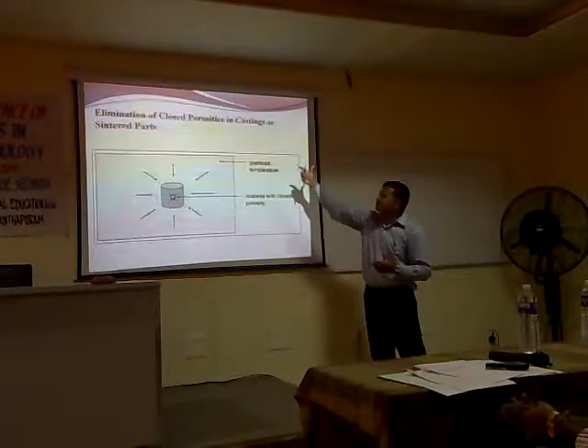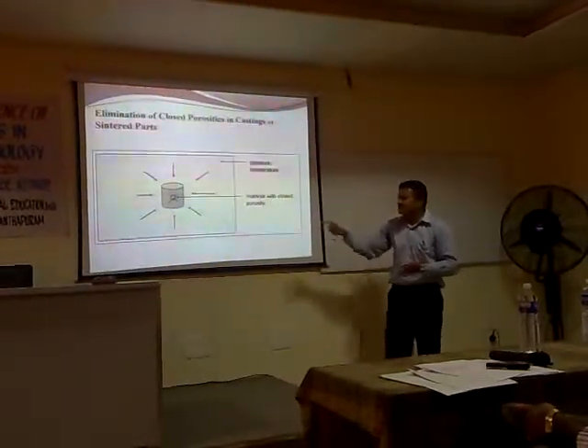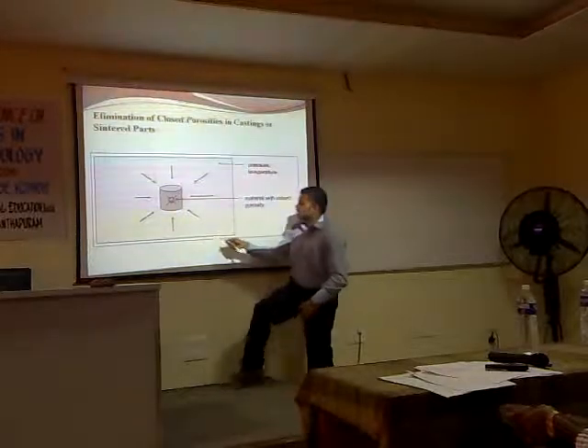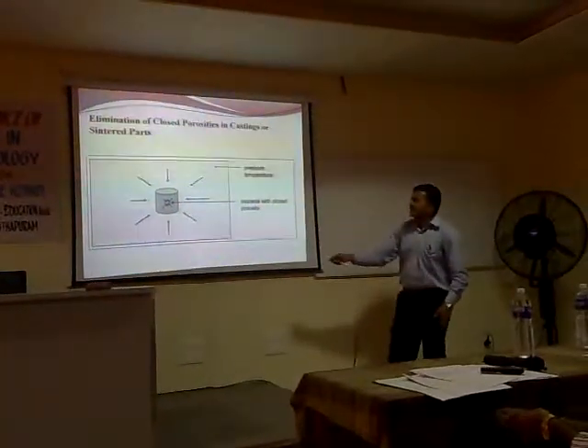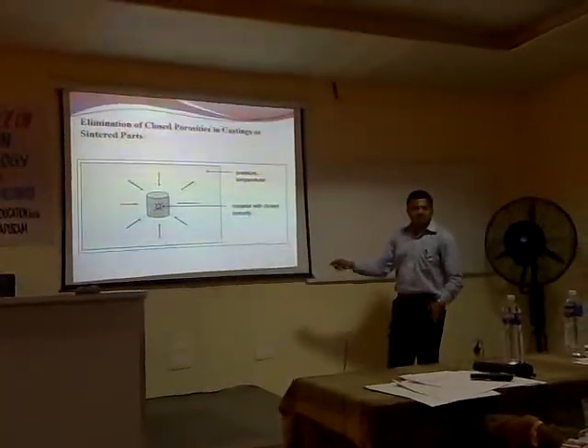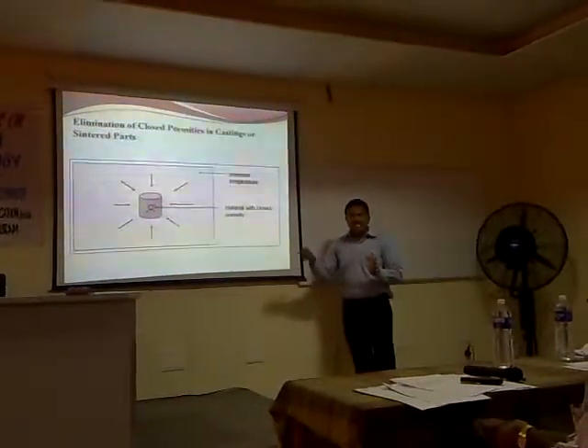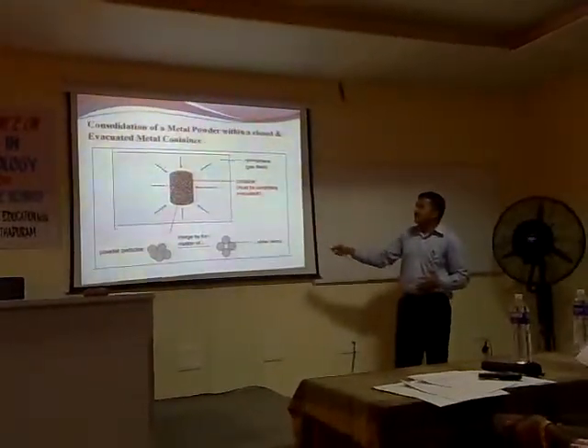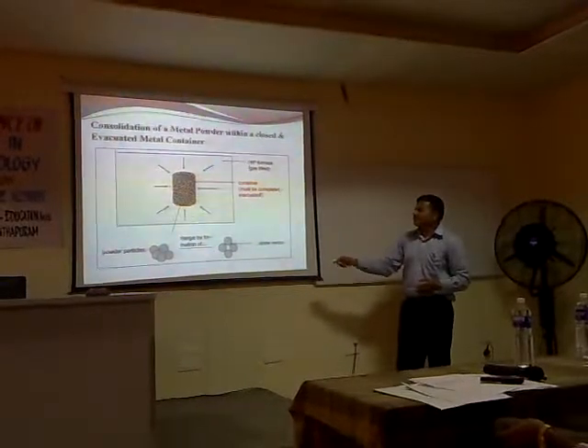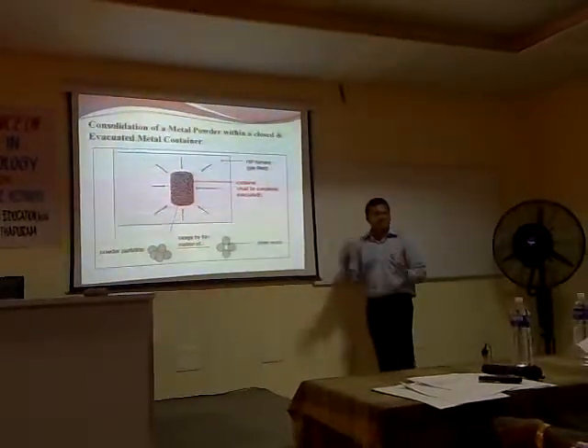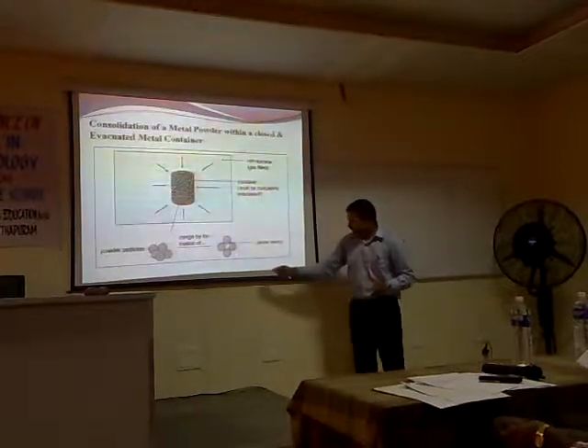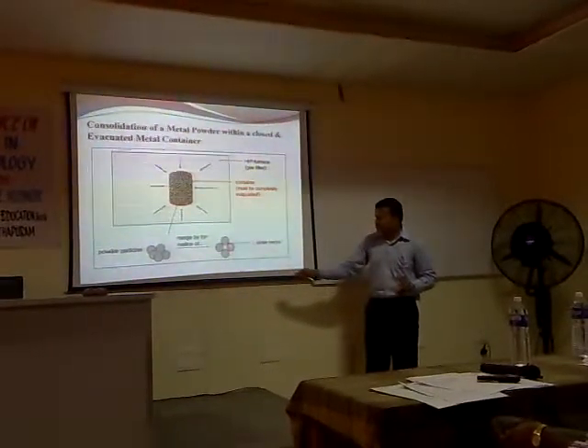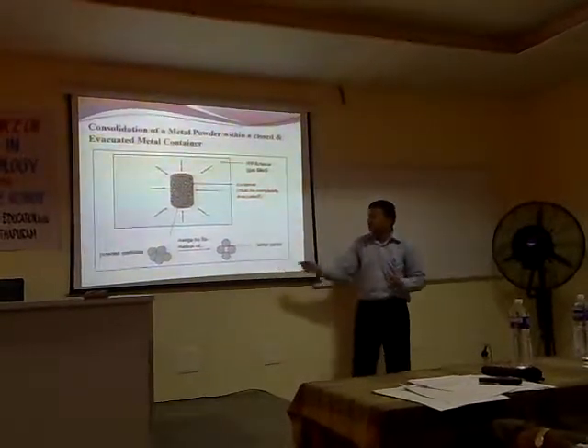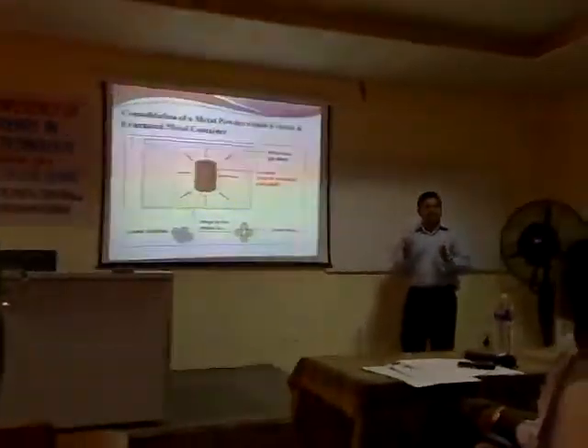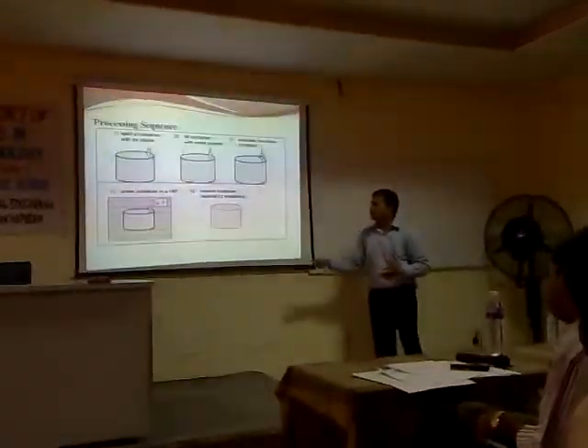The first one is elimination of closed porosities in castings or sintered parts. Here, powder particles are placed in a container and very high pressure is applied on these particles so that all the porosities are eliminated. And then high temperature is applied. Due to high temperature, around the sintering temperature of these particles, the particles which are in intimate contact with each other undergo local welding at these points, as indicated here, and these particles aggregate together to form the final product shape.